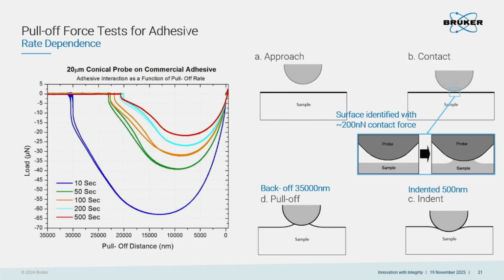So this is the very first example I will show to you, talking about the rate sensitivity or the speed sensitivity. We use exactly the same force to test a uniform polymer, and you can see that we just change the time for the testing. We can use a very high speed and get the results as the blue curve shown here. You can see that the pull-off force is much, much higher than the results collected using a long testing time, that means an extremely lower speed. So that is the very first example I would like to show to you about polymer characterization, which is the so-called rate or speed sensitivity.